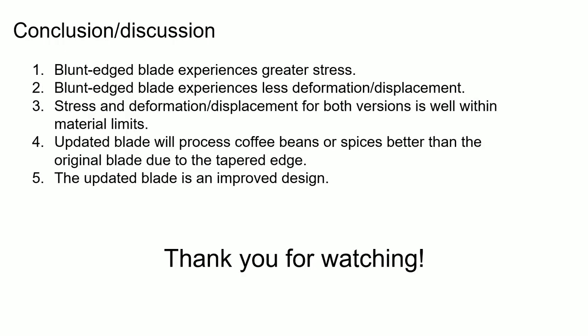In conclusion, the blunt edge blade experiences greater stress than deformation due to the greater surface area exposed to the material being ground. This behavior was apparent in the high stresses at the blade shaft interface where the metal of the blade is thinnest, as well as the greater deformation at the tip of the blade. The stress concentration area is naturally the highest stress location due to the moment around the center of the blade caused by the applied load.